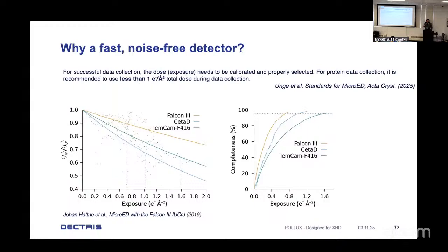So why do you want a fast noise-free detector? This is a paper by Tamir's group referring to MicroED. And they say that the dose that they recommend is less than an electron per square angstrom. So radiation damage is a severe problem. This is also from Tamir's group, from Johan Hattne, showing the I over sigma as a function of exposure. And you see that the noisier the camera, the higher the exposure that you require in order to achieve a given I over sigma. So with the CetaD being more noisy than the TVIPS camera and the Falcon 3, if you have a noise-free detector, you can achieve the highest I over sigma at the lowest dose.